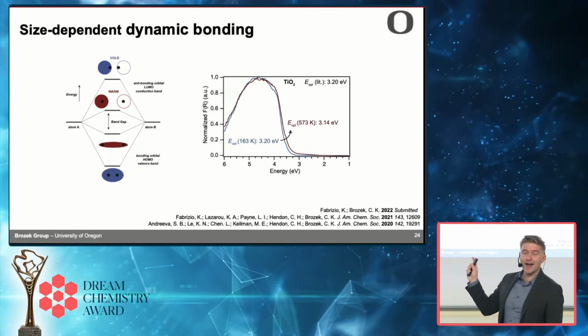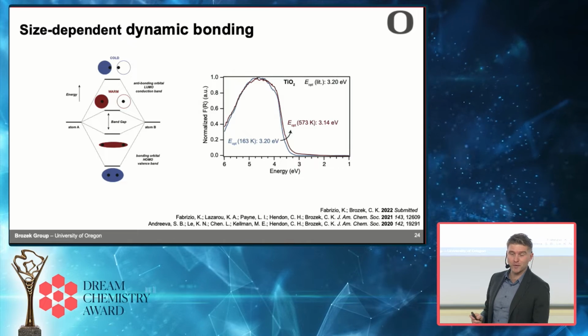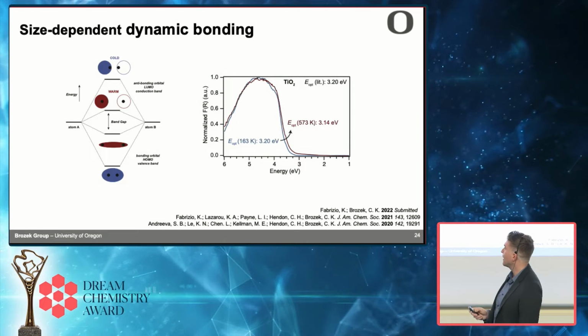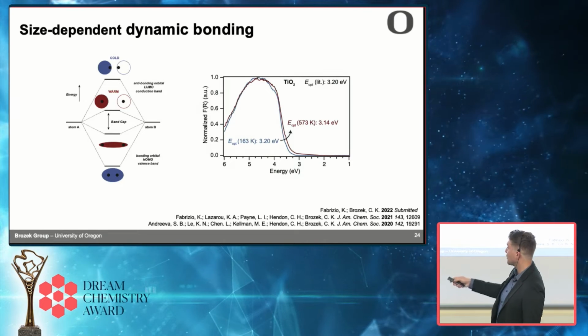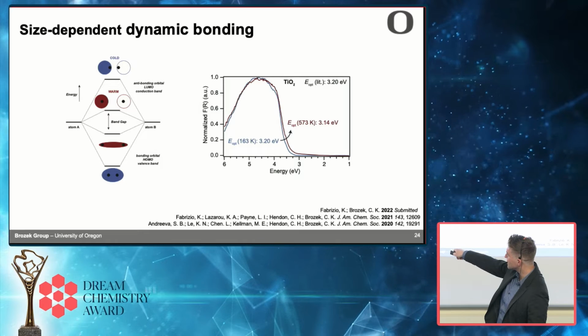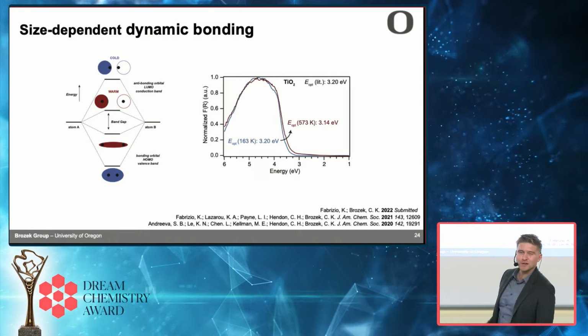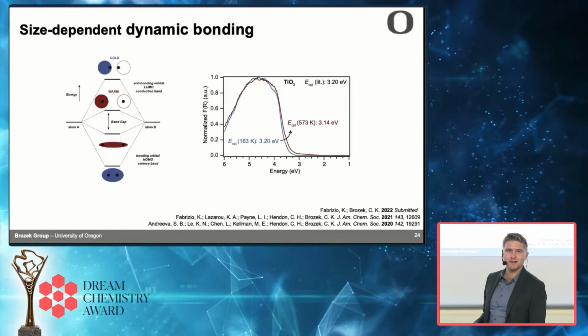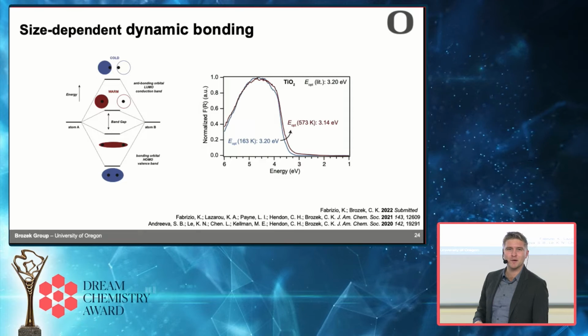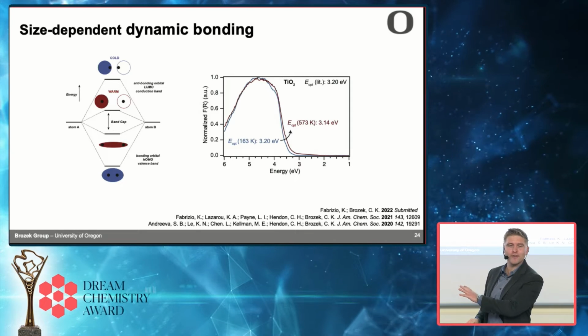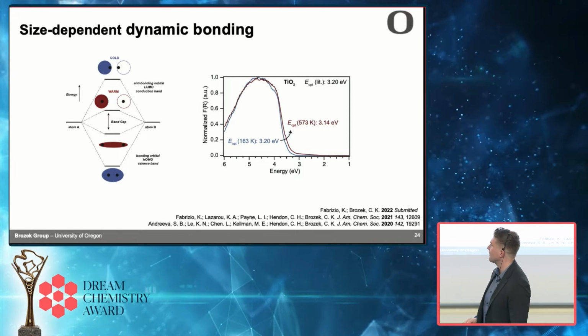I had a hard time finding actual spectra for what this looks like because the effect is so subtle. And so we collected this data ourselves for TiO2, and this little shift here is what you would expect for TiO2. This is what people had analyzed previously. It shifts the same amount that people had reported. So a very minor effect, minor but reproducible effect.